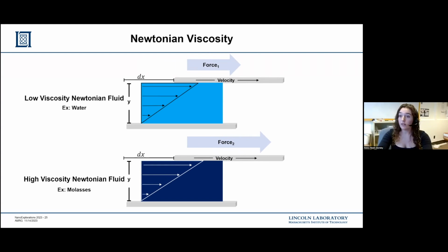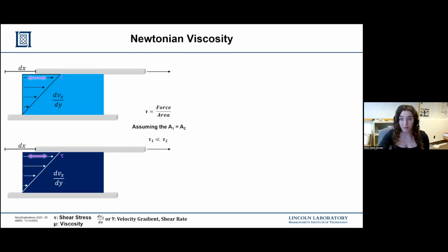And now if we compare the low viscosity and high viscosity systems, the velocities are the same, the velocity gradients are the same. However, the amount of force required to move the low viscosity fluid the same amount as it takes to move the high viscosity fluid is significantly less. I'm going to quickly change our vocabulary. If you divide force by area, you have shear, in this case, shear stress, which is represented by tau. We are going to assume that the two areas are the same. So we can say that the shear stress applied to the low viscosity fluid is lower than the shear stress applied to the high viscosity fluid. Completely the same principle as when we were describing this in force.